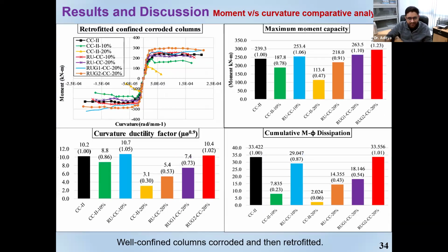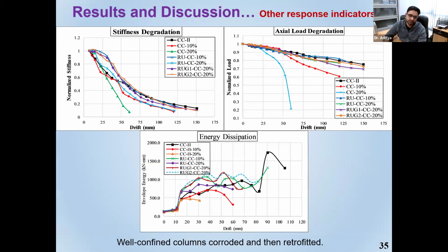Same goes with the other types of indices. I won't spend much time here, but similar trends were noted here as well: a reduction during corrosion, then a slight increase, and then a reasonably good amount of response in the post-peak or peak response domain. Same goes with the stiffness degradation, axial load degradation, and energy dissipation. These are also very important indices when it comes to the seismic response.